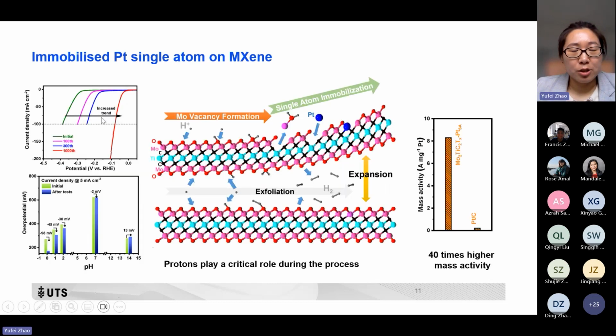This is the LSV result we have achieved during this electrochemical process. From the initial cycle to the 1000th cycle, we can see the performance increased from initial to 100 to 300 to 1000 cycles. That means during this process, the MXene has been exfoliated and also the platinum single atom has been deposited on the MXene.